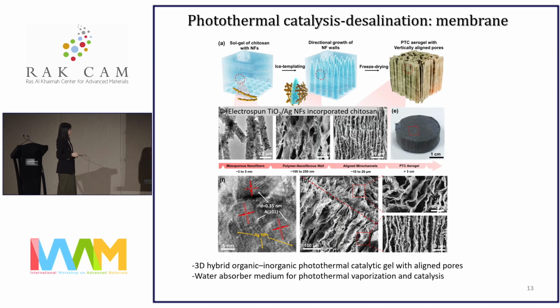With the PMD design in mind, we have prepared a 3D hybrid organic-inorganic photothermal gel with aligned pores, and this can be done by incorporating TiO2 silver nanofibers into a chitosan matrix by a directional freezing method. The TiO2 nanofibers are cross-linked and very well dispersed in the chitosan matrix, which is shown to have aligned pores as well as lamellar walls. And the chitosan is not chosen at random. It has superior water-absorbing properties to allow the replenishment of the water, which is needed for the photothermal vaporization and catalysis.